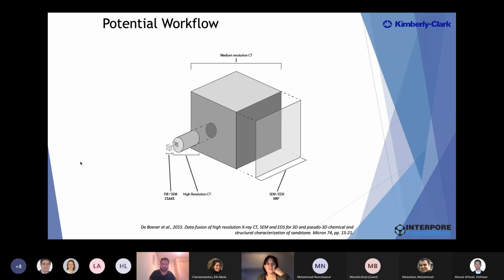Or you can do a medium resolution CT scan, see the zones, then take subsamples and go for higher resolution. And if this high resolution is not good enough in resolution style, you can even take subsamples and combine this with focused ion beam scanning electron microscopy, or coherent small angle scattering, or go with your samples to the synchrotron for higher resolution if needed.